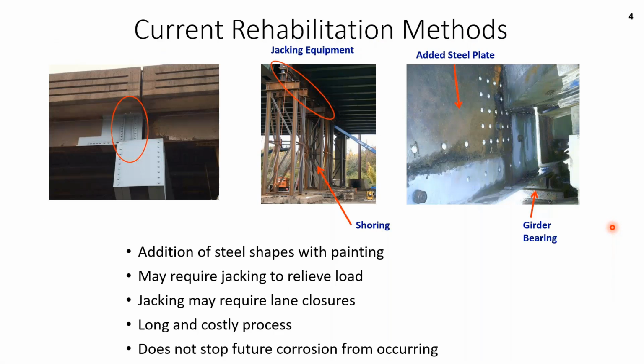So how do we currently repair this? We see pictures like this from all over the country. It's very common to clean the steel, bolt plates on, bolting angles, plates. Sometimes we're cutting portions of the flange away. Sometimes we're welding, we're painting. There's an awful lot going on at these beam ends. And we've seen repair costs for some of these beam end repairs exceed $30,000 to $40,000 per beam end.